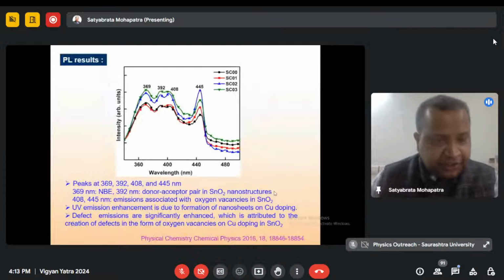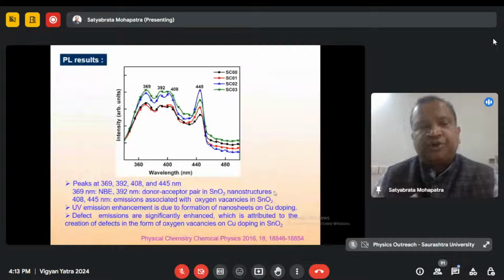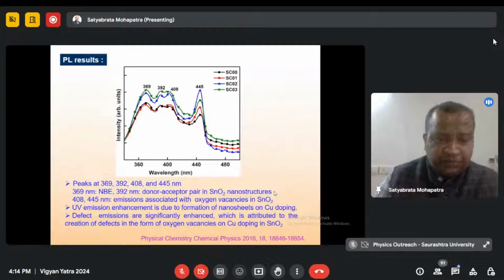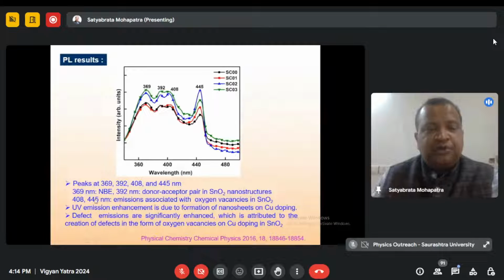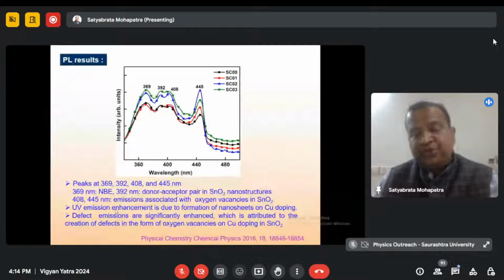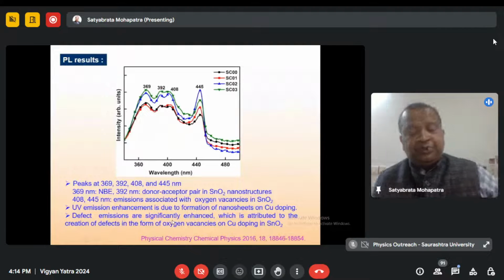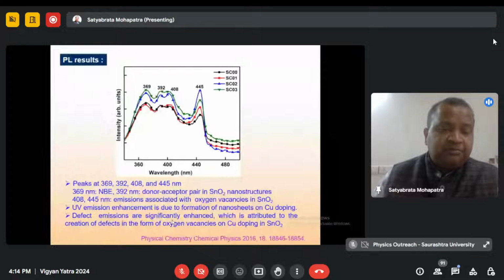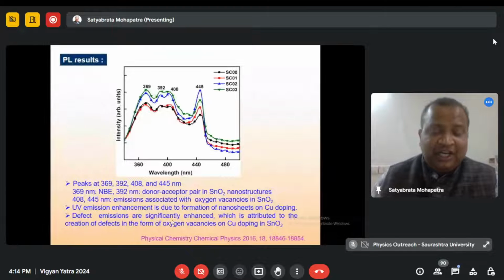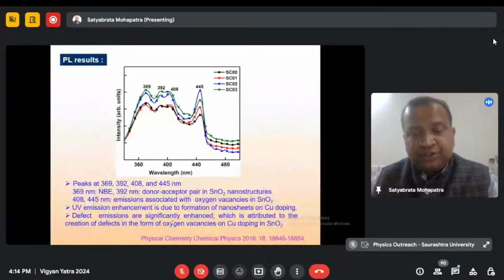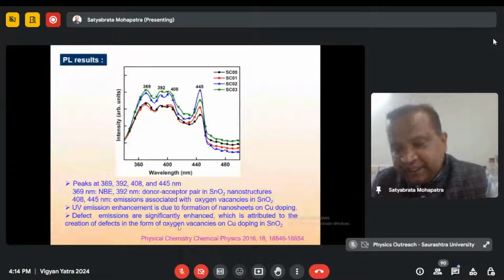The photoluminescence results show peaks at 369, 392, 408, and 445 nanometer, and you can see distinct emissions from the oxygen vacancies around 408 and 445 nanometer, and there is an enhancement in this defect luminescence upon copper doping, and the UV emission enhancement is due to formation of nanosheets upon copper doping. And this is interesting. This is clearly seen in the FESEM images as well, where copper doping changes the structures into more nanosheets. And this will have an impact on the gas sensor response, because you need to have defects for efficient adsorption of the gas molecules. And these defect emissions are significantly enhanced, which is attributed to creation of defects in the form of oxygen vacancies. Intensity versus wavelength, UV.